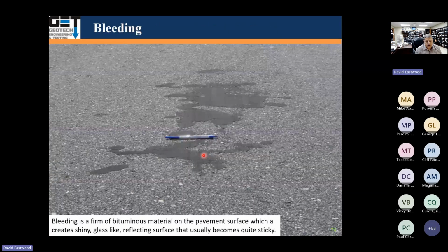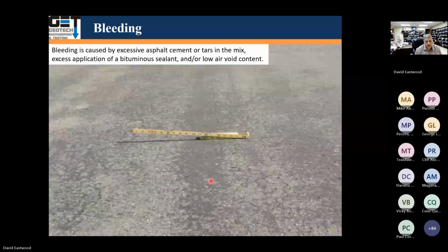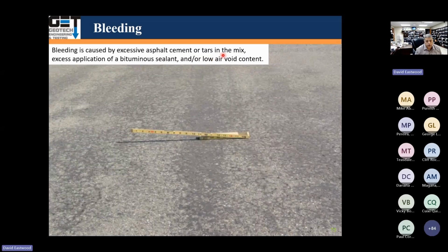Bleeding. Bleeding is basically a film of asphalt material on the pavement surface, which creates a shiny, glassy, reflecting surface that usually becomes quite sticky. It is caused by excessive asphalt cement or tars in the mix of the asphalt.